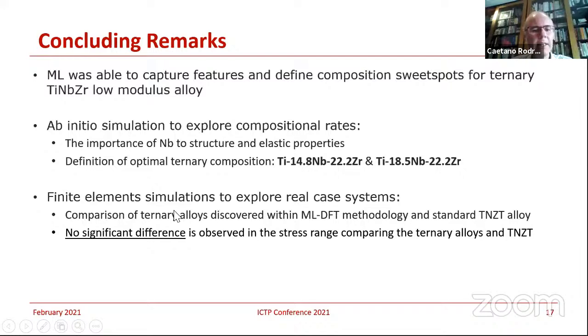And finally, the finite element simulations allowed us to explore real case systems, and you have a very good combination of the ternary alloys that you discover, compared with the standard TNZT alloy. Basically, you didn't see any significant difference between the stress response of those alloys.